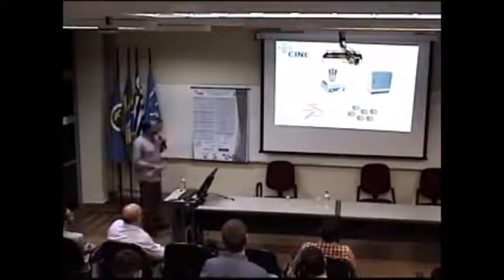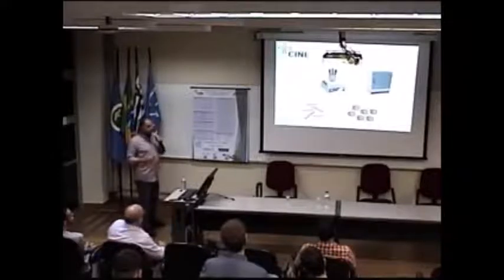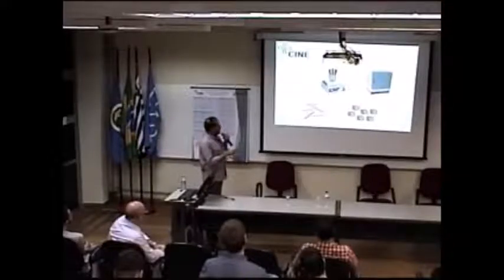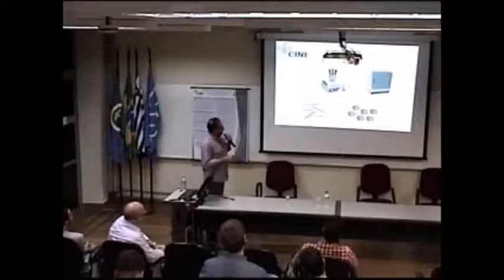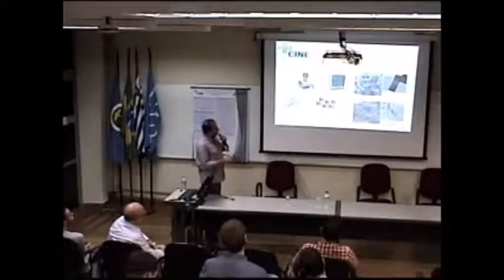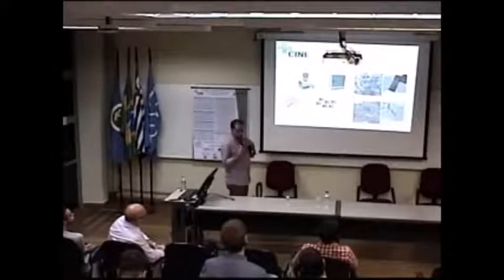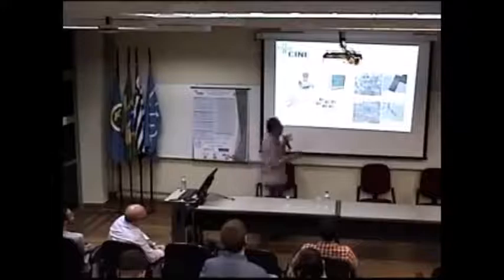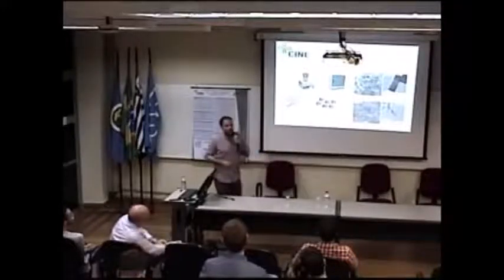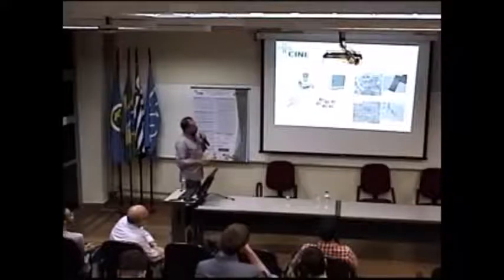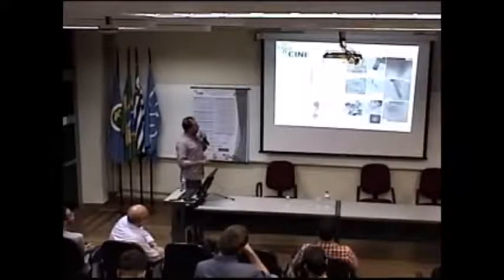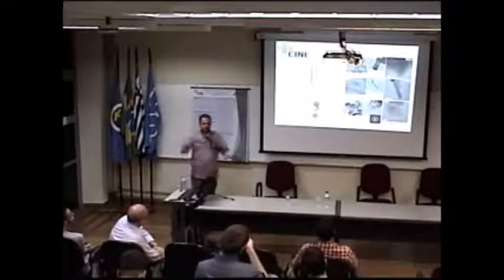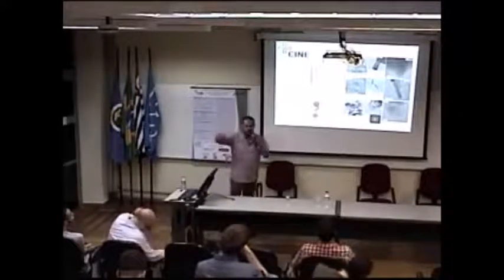And one of the things that we have been doing is also very interesting for the theoreticians here. We have been producing ceria, but not only ceria, we are trying to control the shape of those crystals. Very smart chemistry guys like you come up with these hydrothermal reactions, and they can control it. Only by controlling temperature, they can come up with different shapes. Very interesting and very beautiful. I love it. It's like the nanocubes. If I were a theoretician, I would say, Fábio, let's talk now. Look at this. So those cubes and those nanorods are produced by the hydrothermal method, and we are using this. Those are single phase. We can produce them with different dopants: gadolinium-doped ceria, samaria-doped ceria, different materials.